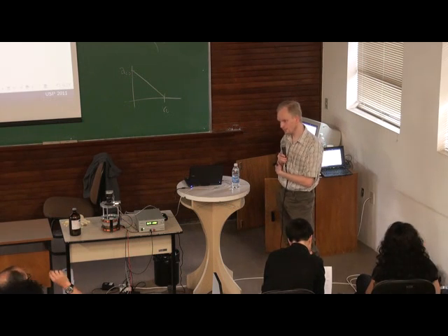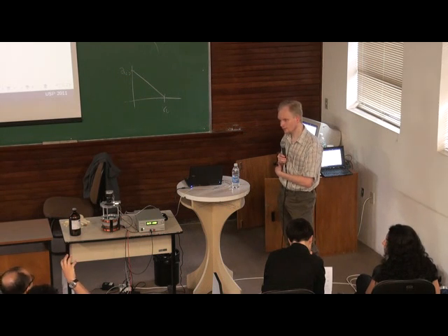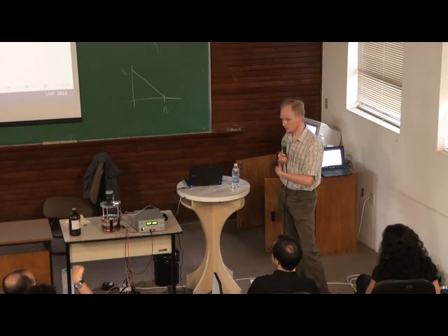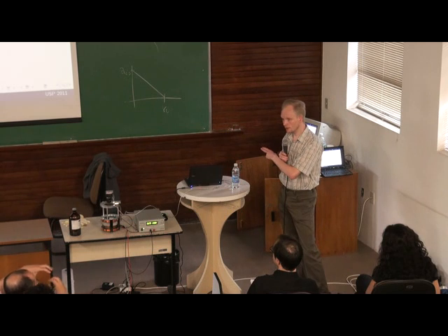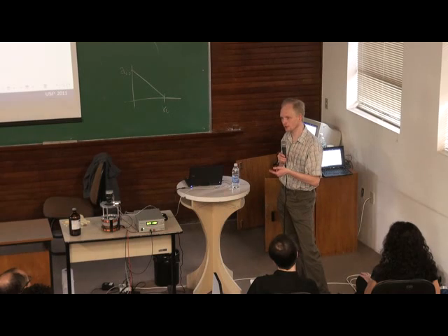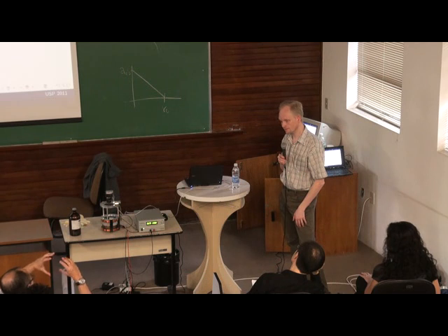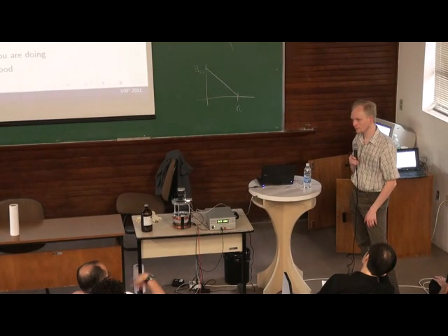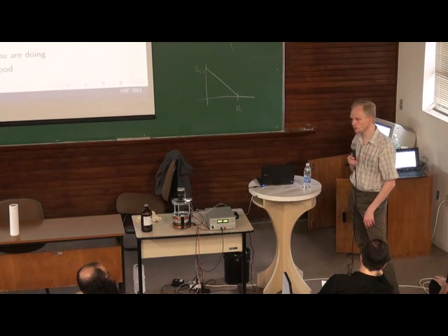Our molecules have dimensions, or you can put a dimension. That's what I did in this surfactant simulation. So the head is twice as big as the tail, for instance, and that again dictates the curvature energy of the micelles. Yeah, because if you have a big head and a small tail, the packing will be different. Yes, yes. And you could see that from the simulation.